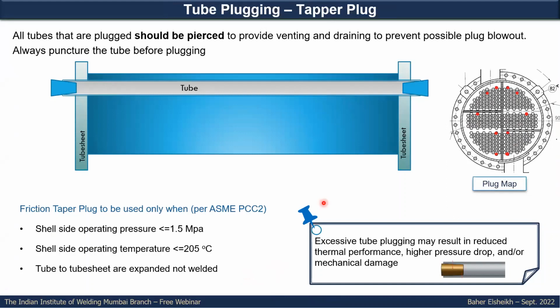For the plugging, we said we have many types of plugs. This is the most common one, or the most simple one, the tapered plug. Tapered plug, as we can see here from ASME PCC-2, is somehow limited to a little bit lower pressure and temperature, and also to cases where the tube-to-tube sheet joint is not welded.